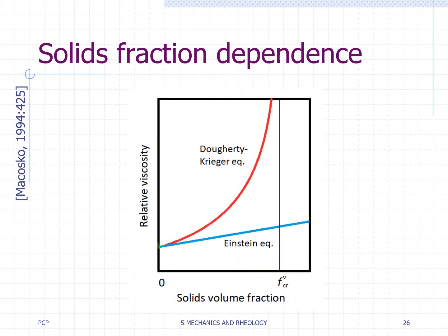The Einstein equation applies to volume fractions less than 0.01, assuring that the flow around a particle does not influence the velocity field of any other particle. At higher particle concentration, the hydrodynamic interactions between particles become important. In those cases, the Dougherty-Krieger equation may be applied.